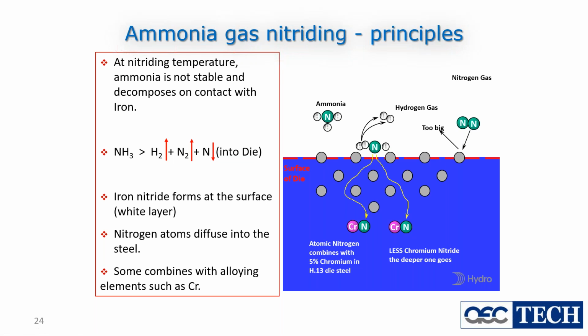This is the process that's going on inside your nitriding tanks every time you run your die. And this surface layer is where all the really important stuff happens, where this dissociation reaction occurs. And I have to stress, it is N, nitrogen atoms, that we want. This N2 here, that's a waste. It just goes away. And we use the chemistry of the gas to try and control it so we make as much N as we can.